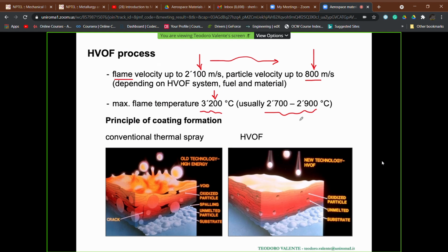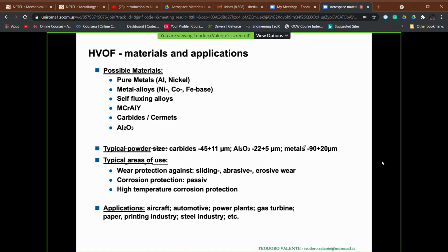technology. The advantage with respect to plasma spraying when we can use HVOF is, let me say, a double one. First, we do not need to use this process in a confined environment. So HVOF is always performed in air. And the second one is related to the fact that the highest velocities of the particles can lead us to very low values of porosity inside the coatings, with mass density which can approach 99% of the theoretical density of the materials when fabricated with another technology.